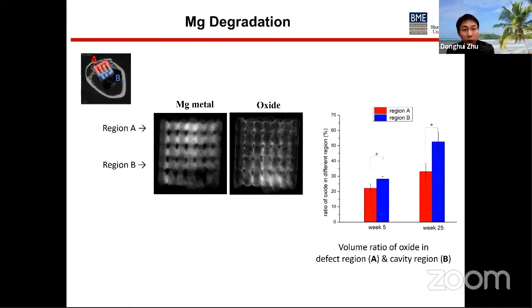Then we look at the two regions, A and B, as I mentioned, corresponding to the bone embedded in the femur and the region exposed to the marrow cavity. The degradation is more aggressive in the cavity B region, suggesting the scaffold in the cavity is absorbed faster. This is actually quite desirable for our implant.